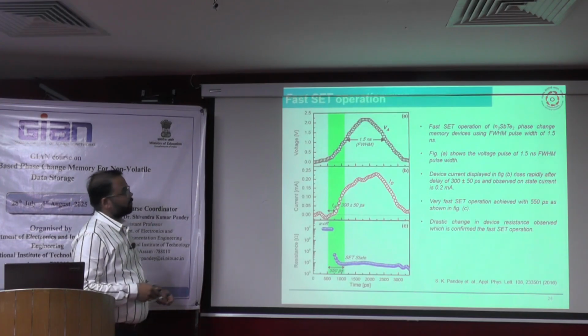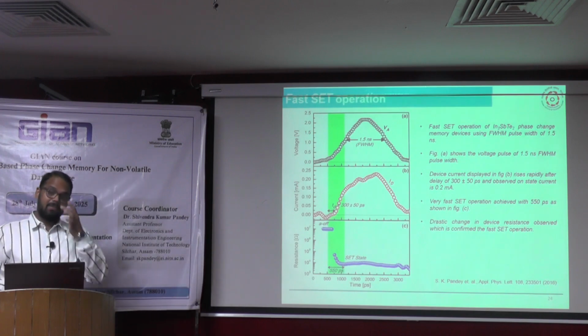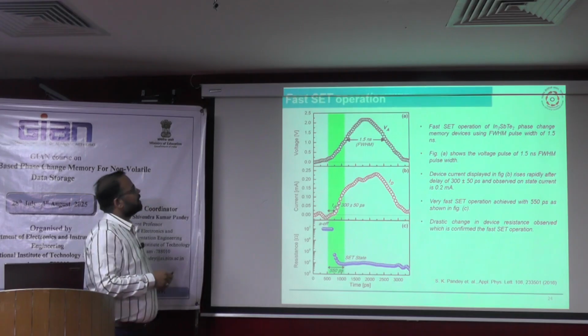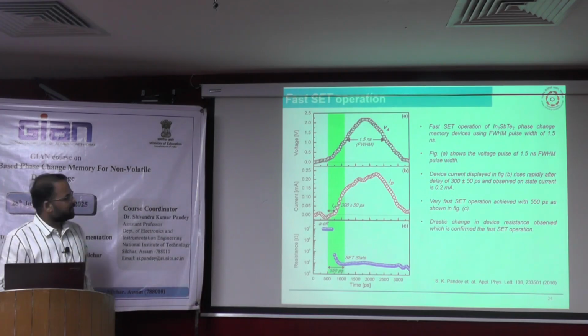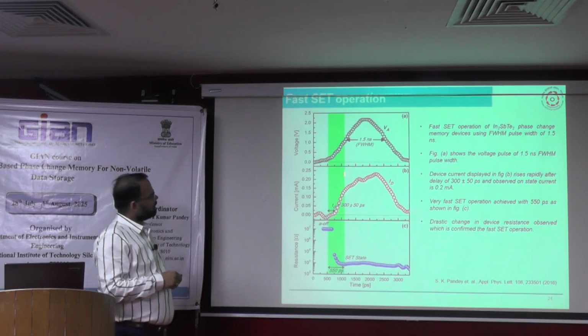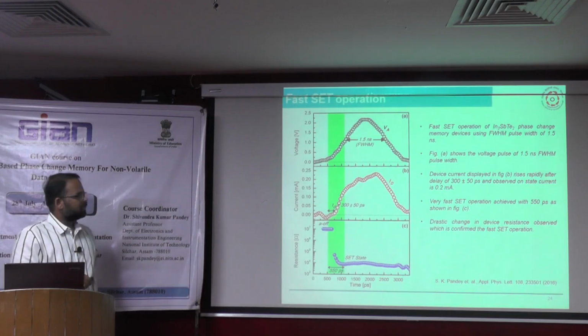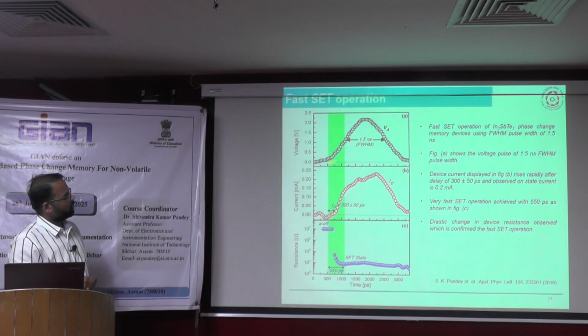And the fast set operation, the way we have seen set multi-level operation during set operation, how it could be for ultra fast switching. So this is a voltage pulse of 1.5 nanosecond pulse width, which has a 1 nanosecond rise time.